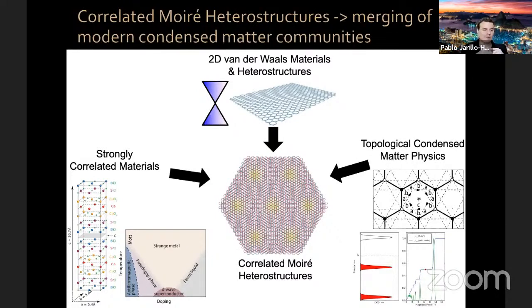For example, if you use a scanning nanosquid and you're looking at quantum Hall physics in magic angle graphene, if you have graphite, you have the Landau levels of the graphite itself interfering with the signal. So it's much better to use metallic gates. Again, there's no particular reason not to use graphite gates. We do use them for a number of our devices, but metallic gates also work and are better for some experiments.